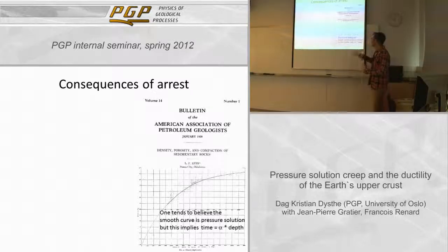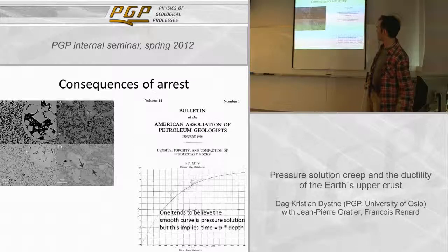Now there's just one problem, and that's that pressure solution is a viscous rheology. It has time in it. So if you leave it at some depth, there is a differential stress, and it will change through time. So if you compare different reservoirs that have different ages, you shouldn't have a common density curve. They should be different because the time is different. But if this curve is due to pressure solution, it means that there is some relation between time and depth, which seems strange for the different reservoirs.